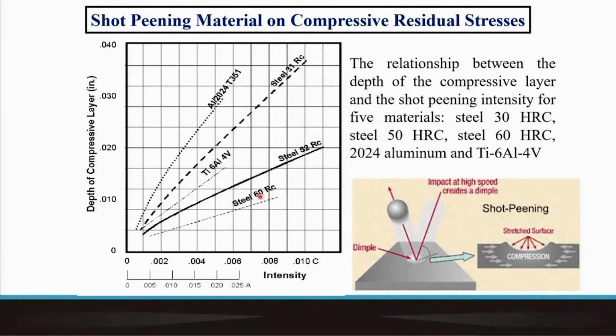So if you do steel with lower hardness and with higher hardness, this is the level of compressive stress and the depth up to which you can create compressive stress. This is steel with higher hardness, and this is aluminum. This is steel with lower hardness. This is titanium and steel with slightly higher hardness. So as the degree of hardness increases, we see the depth of the compressive layer that is formed is shallower. So obviously, it will not fetch the same level of fatigue strength or improvement in fatigue property as we can see with softer materials like aluminum or soft steel or titanium alloys and so on.